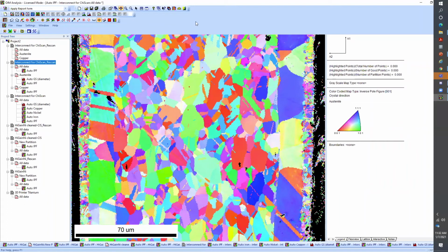So yes, I would slow down. In that case, the first thing I would do is go out of super mode. Super mode is essentially using the higher range, but it's easier to saturate the camera. By going out of super mode, you would now be on the lower end of the range, which gives you more range to go higher. Does that make sense? So leave super mode and go to the normal mode.